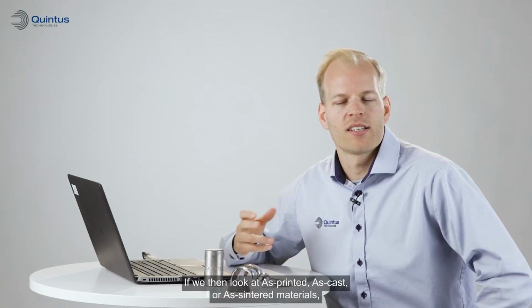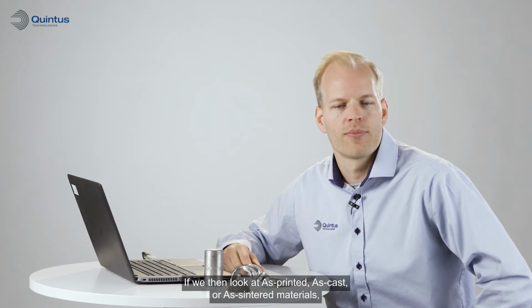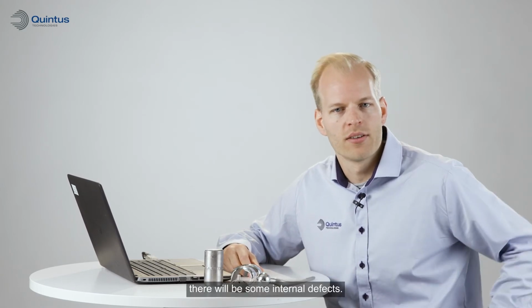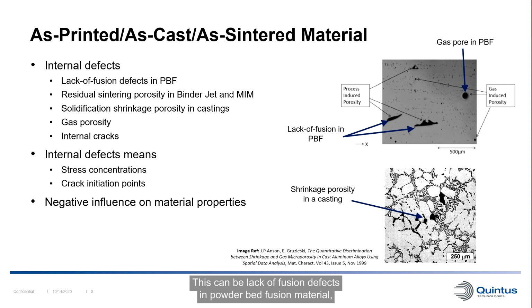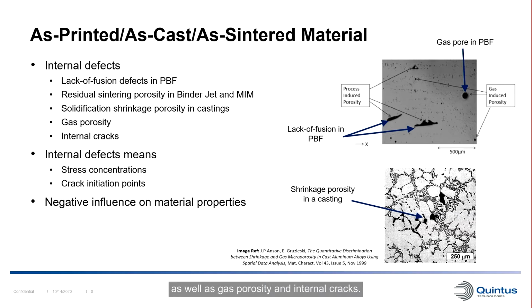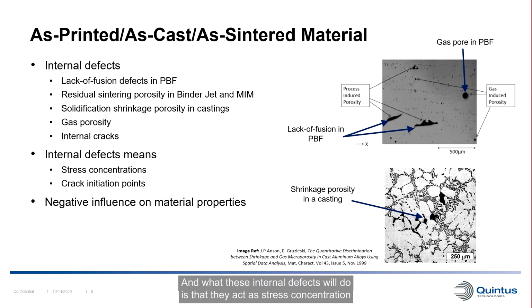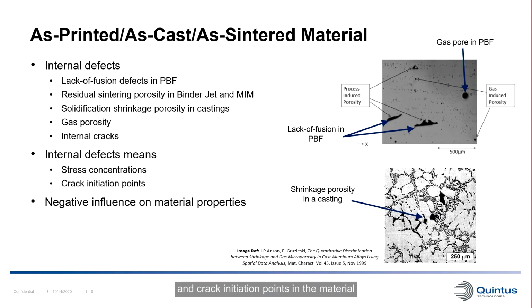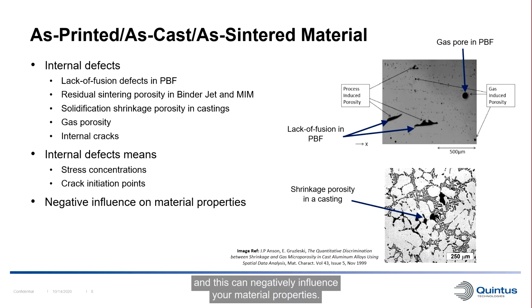If we then look at as-printed, as-cast, or as-sintered materials, there will be some internal defects. This can be lack of fusion defects in powder bed fusion material, residual sintering porosity for binder jet and MIM, solidification shrinkage porosity in castings, as well as gas porosity and internal cracks. What these internal defects will do is that they act as stress concentration and crack initiation points in the material, and this can negatively influence your material properties.